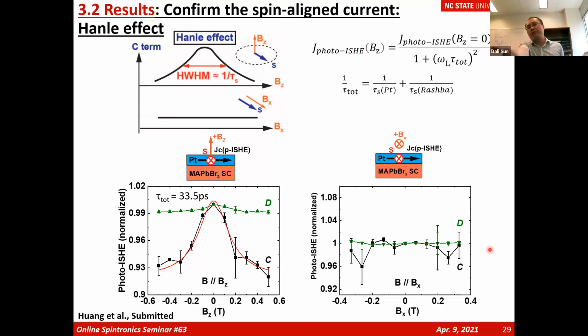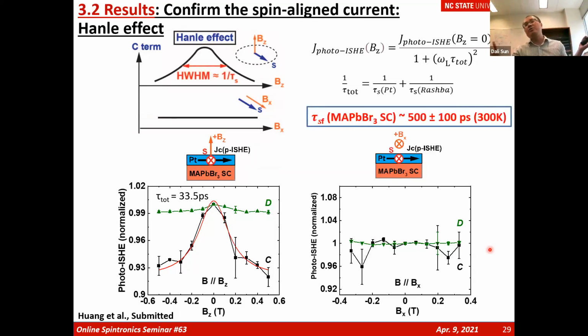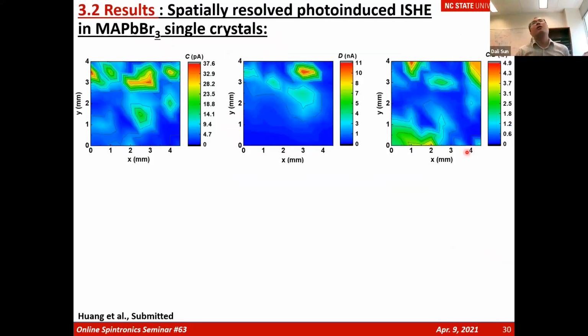By taking advantage of the photo-induced ISHE effect, we are able to estimate it. The spin relaxation time can be up to 500 picoseconds at room temperature. More or less, roughly, this result is consistent with our previous spin pumping result, like 200 picoseconds, demonstrating the existence of the Rashba effect. We can also do mapping. We can do the photo-induced ISHE across the whole crystal to study which part gives us a strong signal, or whether it is uniform, because of the interfacing effect, probably we would see uniform distributions.